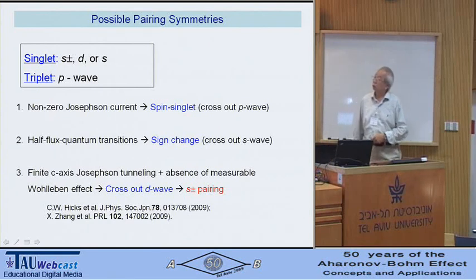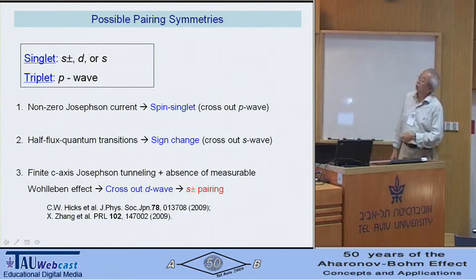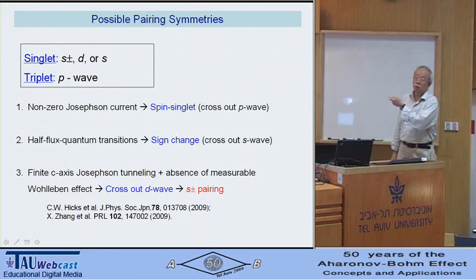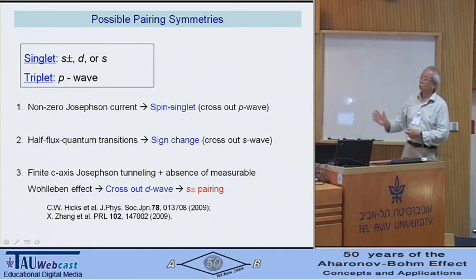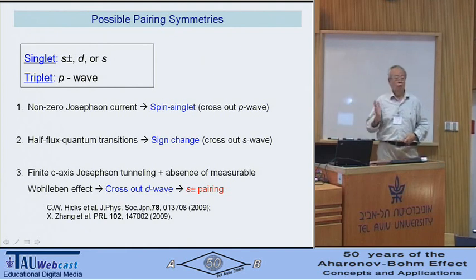Okay, now with this, we're in a position to say something. Since we have a non-zero finite Josephson current, we say it's a spin singlet. The half-flux quantum told us there's a sign change in the supercurrent flowing through the sample. And then we rely on other people's work published in the literature, which I cited here. And they clearly show it's not D-wave. So if you use that to rule out D-wave, then our experiment represents the first definitive experimental evidence to show the new superconductor is S plus minus.